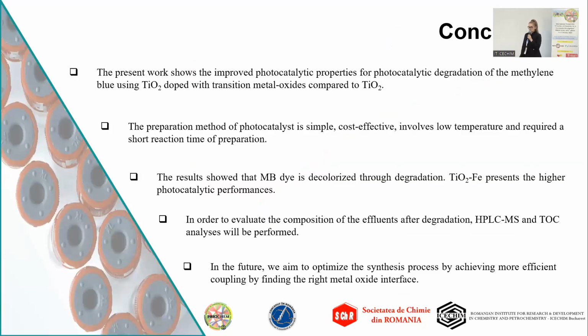In conclusion, the present work shows the improved photocatalytic properties for photocatalytic degradation of methylene blue using titanium dioxide doped with transitional metal oxides compared to titanium dioxide. The preparation method of photocatalyst is simple, cost-effective, involves low temperature, and requires a short reaction time of preparation. The results show that methylene blue dye is decolorized throughout degradation. Titanium dioxide doped with iron presents the higher photocatalytic performance.